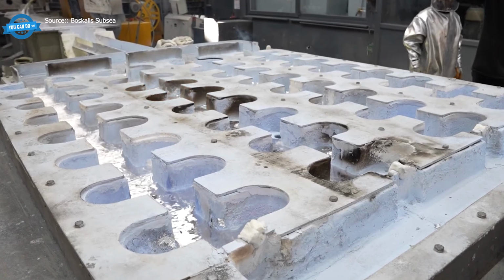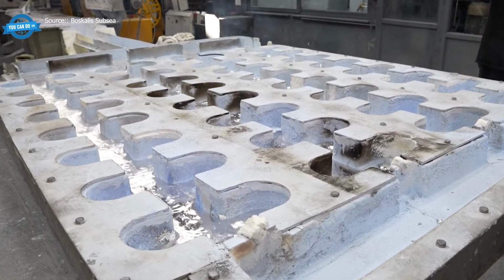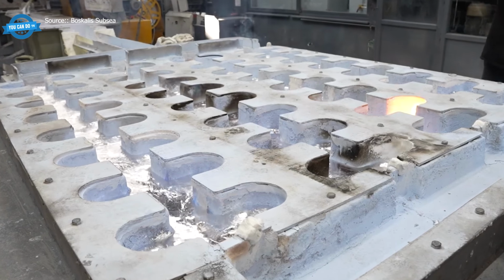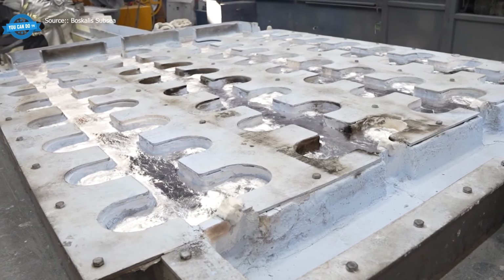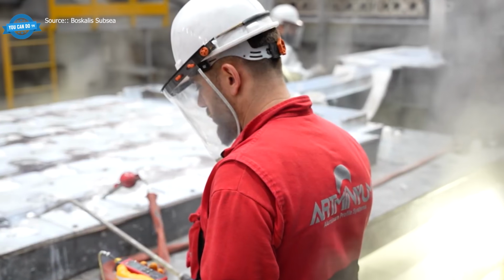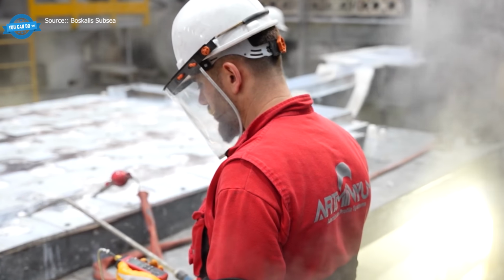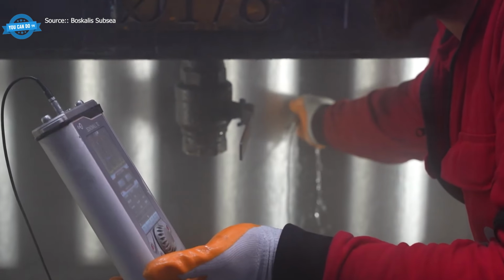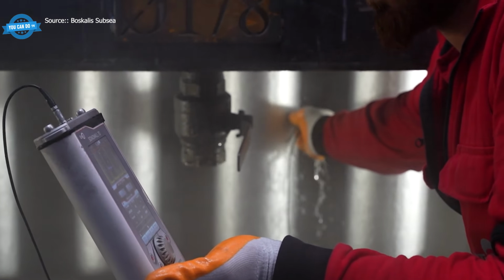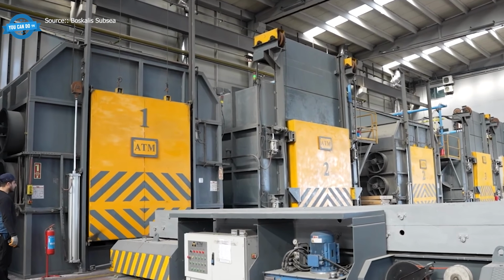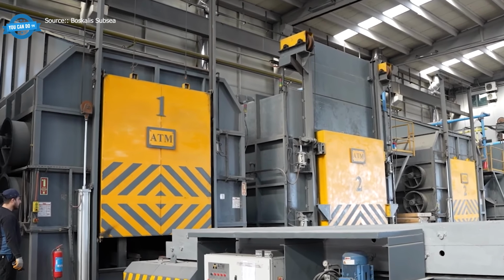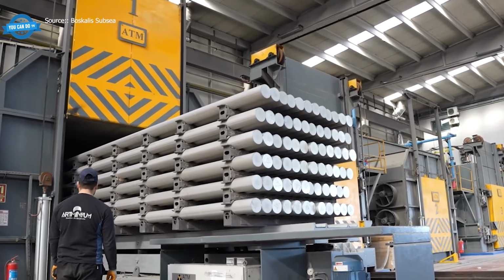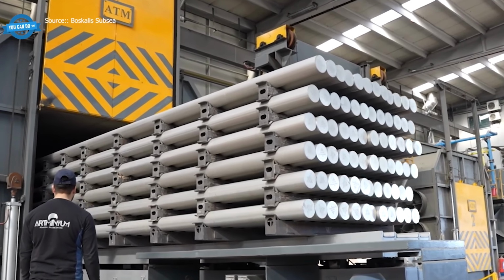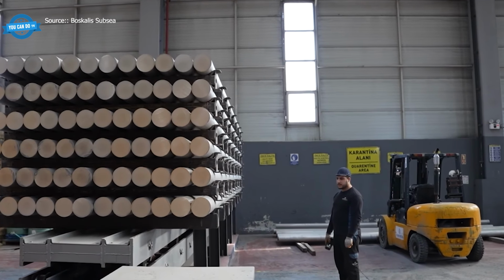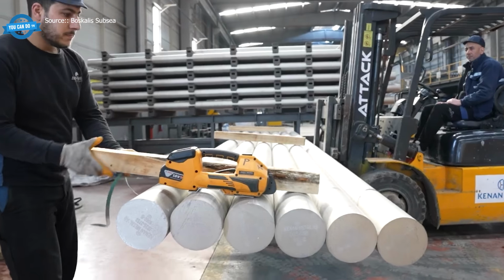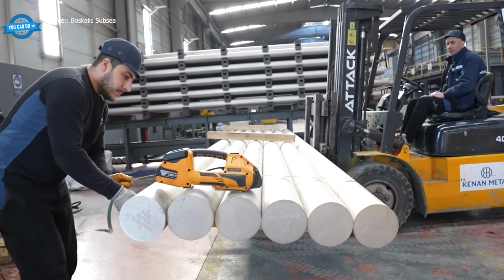A cracked billet fed into an extrusion die wrecks the die on the first stroke. That die costs 6 figures. Foundries producing billets run 24-hour shifts, with molten aluminum arriving from melting furnaces and finished billets being cut, marked, and stacked for shipment. Furnaces hold thousands of pounds of molten metal at a time. Every step is metered: flow rate, temperature, alloy composition, because the customers downstream have tolerances that leave zero room for improvisation.